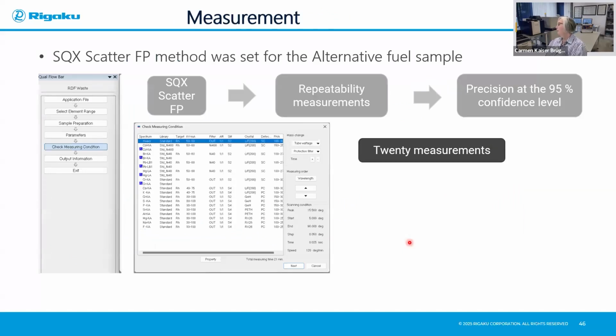How do we set up the analysis of the alternative fuels? It's very easy for us to create a method. So this is the example of the method that we can create. And we can also optimize or make the measuring conditions better by changing certain parameters. For example, we can make fixed angle measurements on certain elements that are important, like, for example, if trace elements are present, then we want to spend longer on the counting of the peak to get a better peak to background ratio. So this is the optimized condition, and we can change this, in a semi-quantitative method.